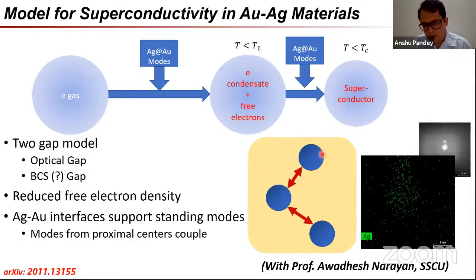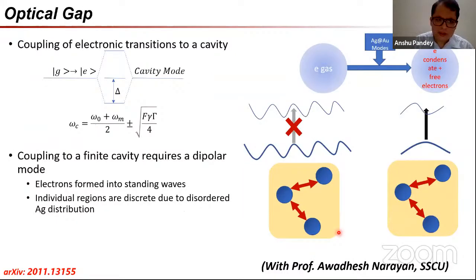How this comes about is that we have silver modes located around each silver nanosphere, and these can couple, giving rise to a cavity. Now, formally, an electron, which is in the form of a propagating wave, cannot really couple to a cavity, but dipole transitions can. Dipole transitions are split by cavities. They can be stabilized as well as destabilized in cavity mode. So you get a dipole-transition-like mode, and you get a cavity-like mode, both of which are of different energies. So while formally propagating electrons can't couple in this way, localized electrons, which are sampling the cavity mode, actually can.